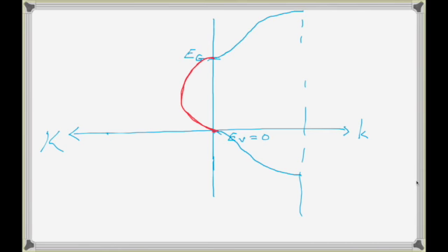But this is what you get from this model, and this is what you're going to, in reality, even with more sophisticated band models, get for any direct gap material. This what they call evanescent band will wrap around and connect the conduction band to the valence band. And the effective mass model, which is parabolic, well, they all start off the same, but this is just parabolic, so it's going to keep going out and down forever.